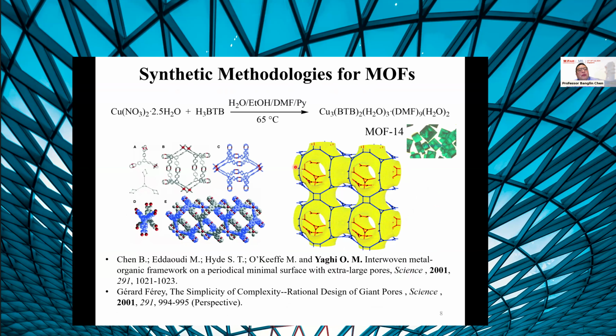The second work is to develop a very simple thermal synthesis methodology to synthesize MOF single crystals in a very short period of time, typically 1 day, because before that, the synthesis of MOFs was quite complicated, typically by diffusion. The first very famous MOF-5 was synthesized by the diffusion method with deprotonation of dicarboxylate. So the yield was low and typically there was a mixture. But with this very simple thermal synthesis, the product can be very pure.